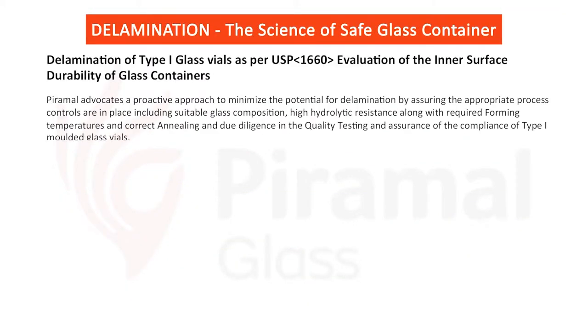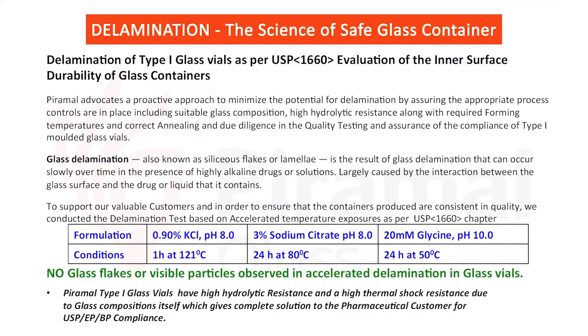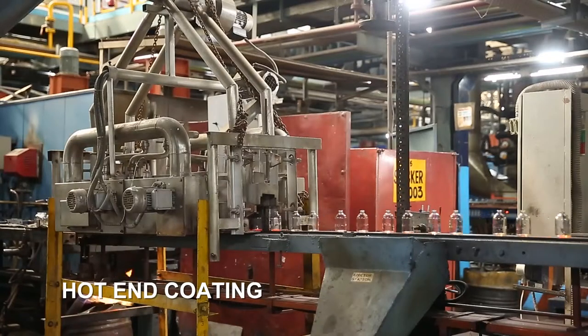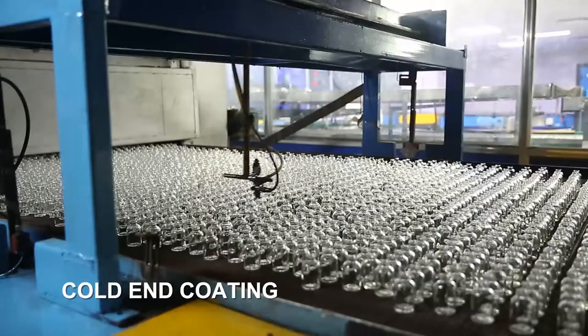Piramal has done study of delamination of type 1 glass vials and certifies that Piramal type 1 vials are in compliance with the requirement of delamination as per USP 1660 for inner surface durability. Piramal type 1 glass vials have high hydrolytic resistance and high thermal shock resistance due to basic glass composition itself, which gives complete solution to the pharma customer for USP, EP, BP, JP compliance and for onco and lyo products by applying hot end and cold end coating on outer surface of vials.